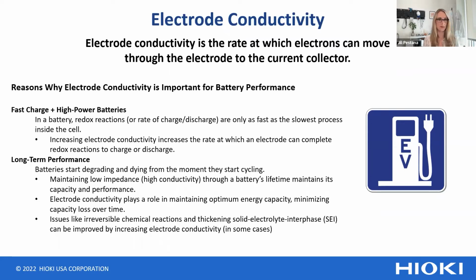I know when I did work with silicon anodes, silicon, as you may know, expands a lot upon lithiation. And so in order to make sure that as it expands, it still remains electrically conductive to the electrode and to the current collector, so that you don't get isolation of the silicon where it no longer dedicates its capacity towards redox reactions. You need to have enough electric conductivity things in the electrode so that it can be electrically conductive, even as the silicon particles may expand or break apart.